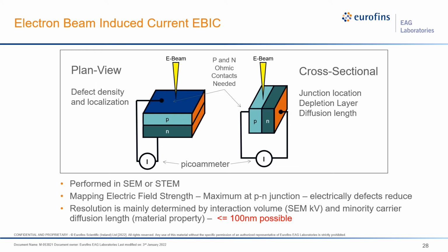So in the case of electron beam induced current, or EBIC, we're going to use the SEM beam to inject carriers into our semiconductor that has a PN junction, and we're going to raster that electron beam across the surface. This technique can be done in either SEM or STEM as well. And effectively what we're going to do is map the electric field strength in the sample.